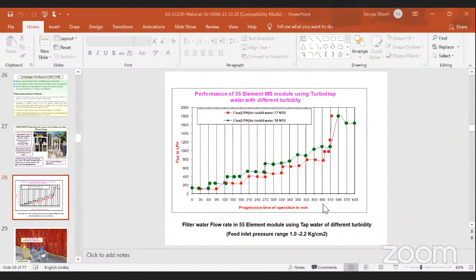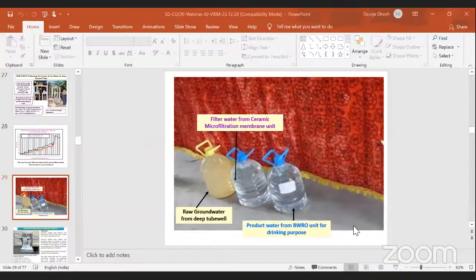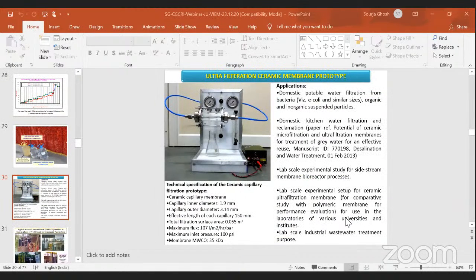This shows the performance of a big ceramic module, that is a 55 element MS module, using turbid tap water under different turbidity. The feed pressure range is 1 to 2.2 kg per cm square. This shows the picture of the raw groundwater collected from a deep tube well and the treated water obtained from the ceramic membrane process.